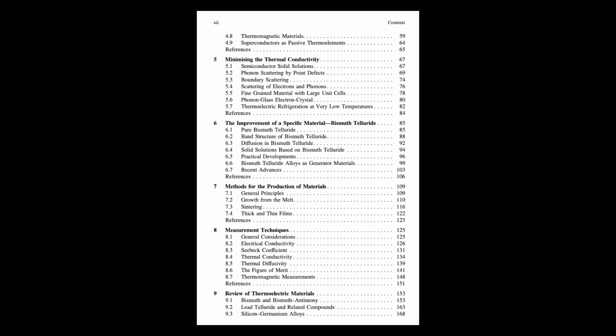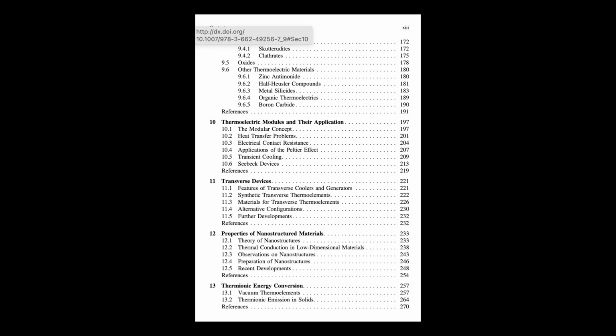Okay, let's broaden out again, materials beyond bismuth telluride, starting low temp. Right, down in the cold, pure bismuth and its alloys with antimony are interesting. Their thermoelectric and especially thermomagnetic properties can be quite good at cryogenic temperatures. Bismuth's Seebeck coefficient, for instance, gets boosted by a magnetic field down there, so they find uses in specialized low-temp coolers and generators.